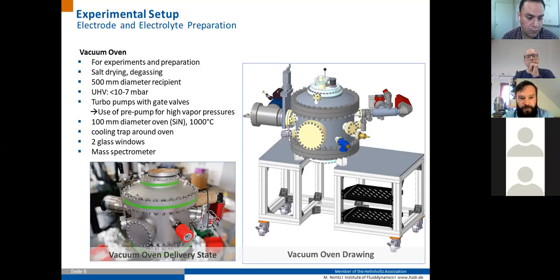And as I said, we will use this vacuum oven to prepare salts, to improve the drying processes of the salt mixtures, and also for experiments and preparation. The vacuum oven itself has roughly 0.5 meter diameter. The vacuum recipient is 0.5 meter diameter, and inside the recipient there is an oven with around 100 millimeter